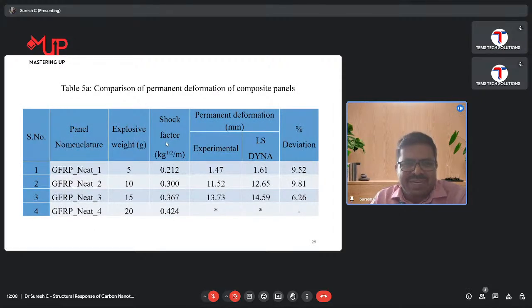So we have compared all the permanent deformations which take place for experimental and numerical, and what is the deviation in the permanent deformation. For 5 gram charge weight, experimentally the total permanent deformation we measured is 1.47. From numerical simulation, we got 1.61. So it is almost close, but since the number is very small, the deviation percentage is almost 9.52.